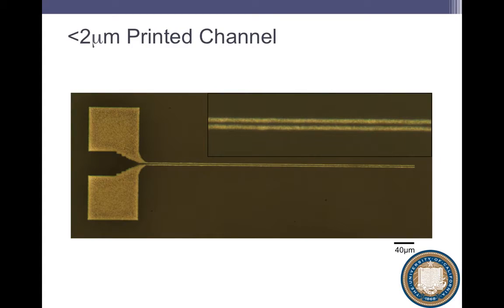Now, what does really good mean? This is what really good means. These are about 1 micron lines, actually 1.5 micron lines. You can see the line edge roughness is really good. Printed at 1 meter per second. These are conductive, printed on large area plastic substrates at 1 meter per second, and we can do this. And there's no reason to stop here. This is just a tooling limitation right now. I absolutely believe we can go further. So gravure can scale at least to 1 micron while maintaining those high print speeds. That's really exciting. Now, this is printing of conductors.